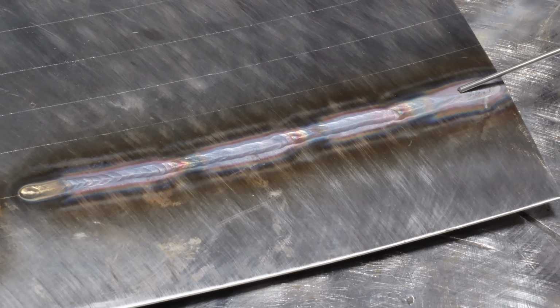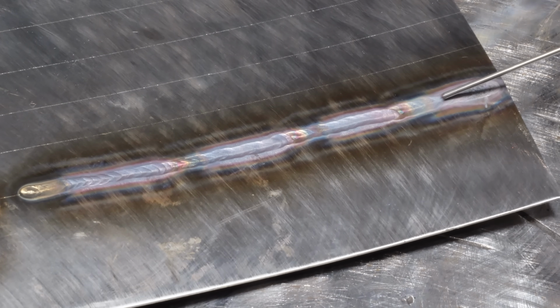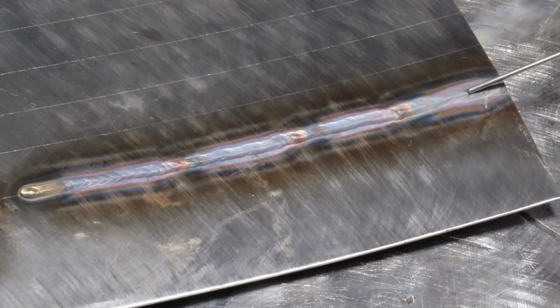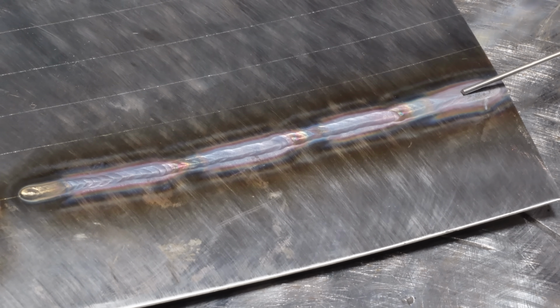If you were to TIG weld up a set of thin wall stainless headers and you had this on every weld, odds are it's going to crack right through there. So you want your bead to be on top of the metal, not sunk in this far.